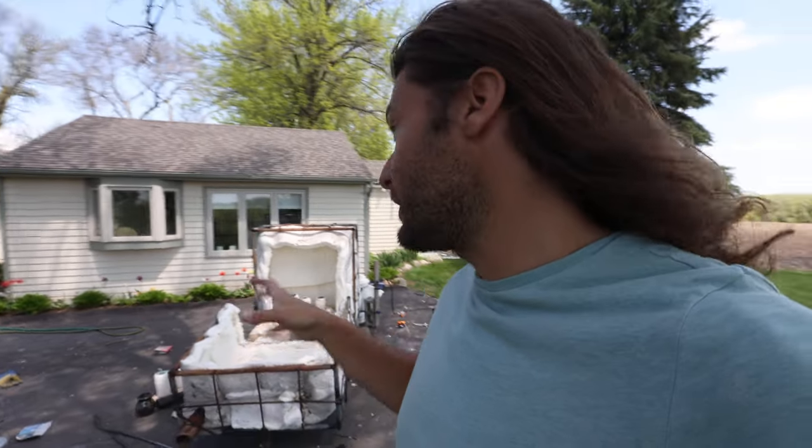Just finished, and definitely didn't get hot enough. This kiln — I think we lost some insulation over the winter. Some critters had crawled their way into the kiln, so I think I need to reline it. There were a lot of places losing heat. After I plugged up some holes it did start gaining more heat, but we should really be at 1800 degrees in like an hour, hour fifteen, and we were at two hours and still only at like 1500. So it was a little disappointing — the glazes definitely didn't mature for the Raku.